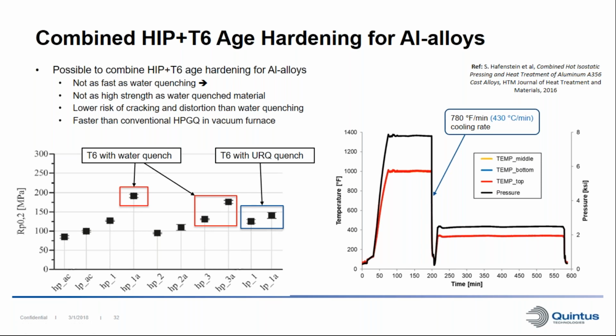And since we're looking at lower temperatures for aluminum here, we also will have lower quenching rates. And one thing to notice here is that we will actually have a slower cooling rate in the material compared to water quenching. And this has actually shown to give slightly less strength than the water quenched material. However, when you water quench aluminum, you could have trouble with distortion and cracking, and this you will not have in a URQ HIP. So in those cases, URQ high pressure heat treatment makes very much sense.